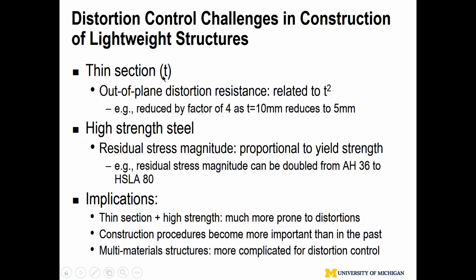So with that in mind, the most recent trend, I think, is lightweighting, and one of the most effective ways to achieve lightweight is multi-material structure. So I'm using this DOE program. And again, most of you are automotive experts, so correct me if I make any wrong statement. If you simply introduce high strength steel, the weight reduction is limited to about 10%. But when you introduce multi-material, that could be composite, aluminum, and high strength steel, depending on where they go, you should use the right material at the right place.